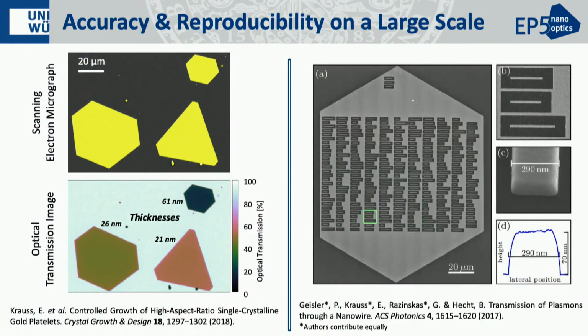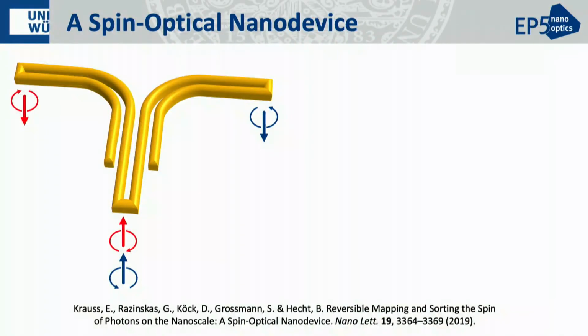I then investigated whether this material was capable of supporting a large amount of structures with a high accuracy, and I fabricated hundreds of structures and measured them and was able to achieve an unprecedented reproducibility for these kind of structures. So then with that I was able to show that they are really able to be used for such optical networks. And then, with this material at hand, I designed a device that can be the building block of optical quantum networks.